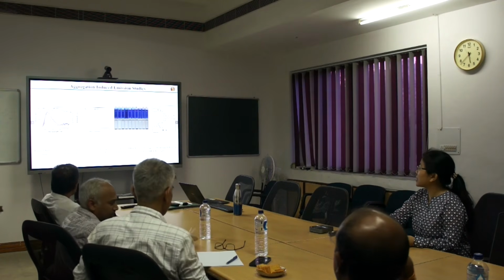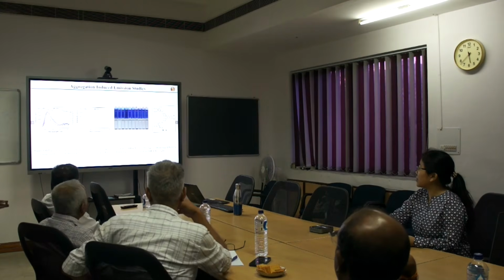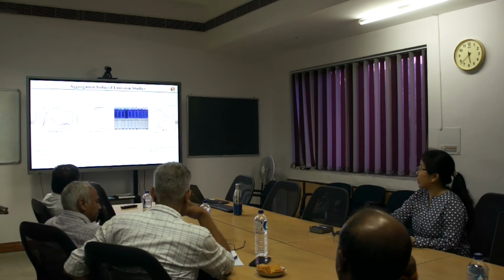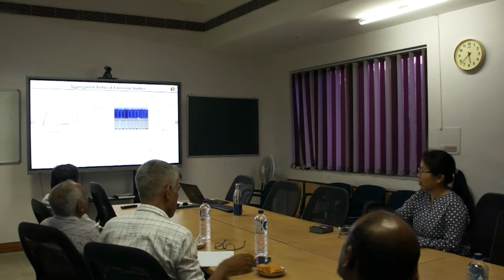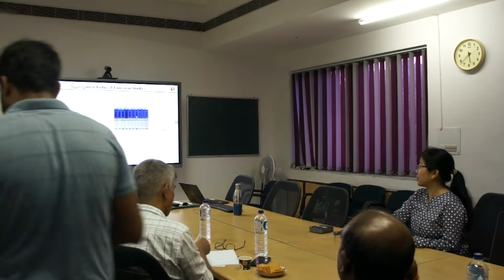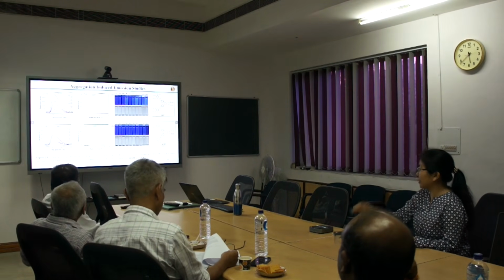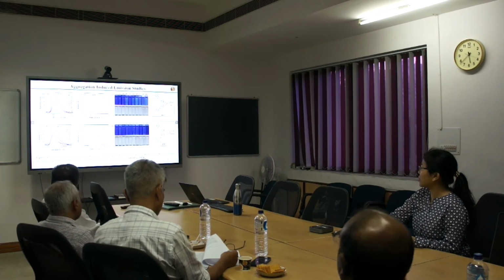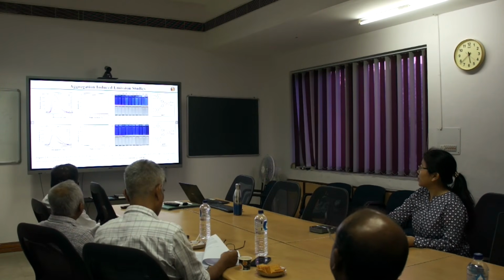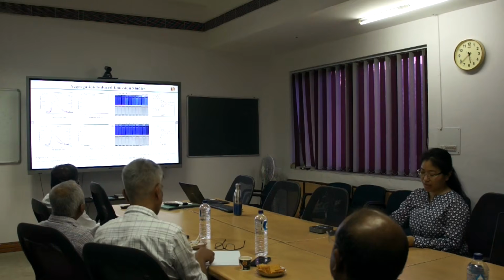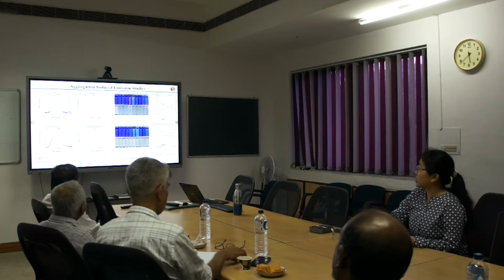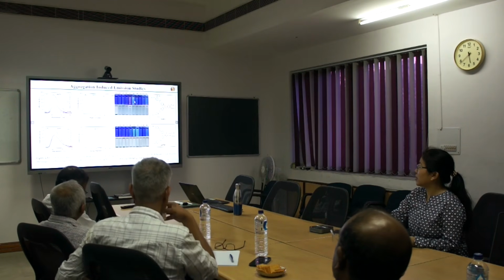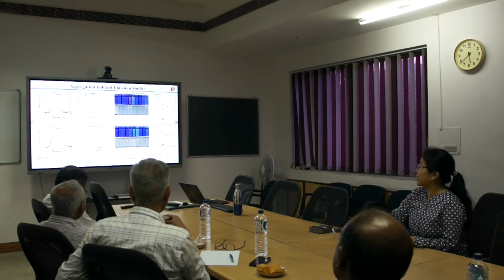And for QECN, this QE series, even though the emission intensity increased up to 80%, the observed enhancement in emission was not that obvious when observed under the UV light. However, in the case of the QVR series, when the alkoxy chains were substituted at positions 6 and 7, with increase in water fraction, the emission intensity was higher at 70%, slightly reduced at 80%, and reduced further at 90%. So for this QVR series, the observed emission intensity was also visible with the naked eye.